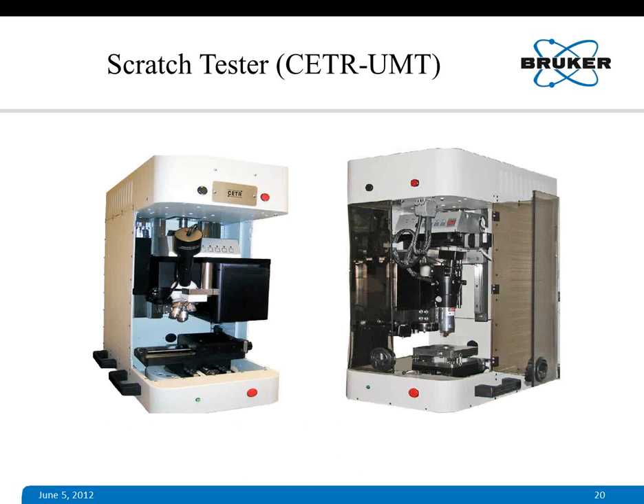This is a picture. There are two pictures here just to show you that it can have an optical system for imaging or AFM. Then it has a head and a profiler for imaging and metrology after the scratch test. It has one drive which actually moves the specimen for scratching. We can also either move the specimen or the tip by using two different kinds of drive systems, slider or linear. And it can accommodate several different probes, say for instance acoustic emission, ECR, ESR probes, which can be simultaneously measured and recorded along with friction force or tangential force and normal force. In the linearly increasing scratch test, normal force is controlled by a feedback loop connected to the sensor.